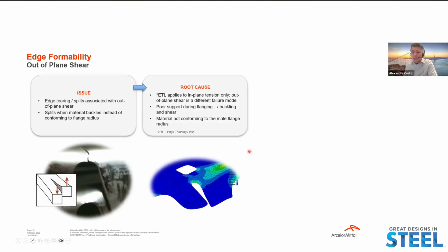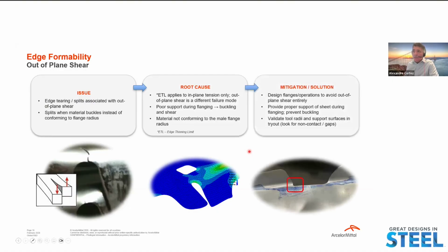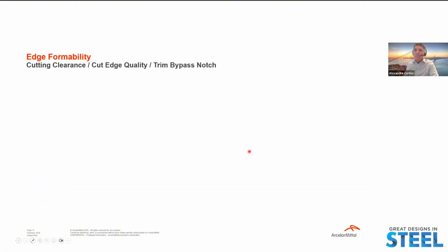As a root cause, ETL applies to in-plane tension, not out of plane shear. It is a different failure mode: poor support during flanging leads to buckling and shear. As a mitigation, design flange operations to avoid out of plane shear, provide proper support of the sheet during flanging, and validate tool radii and support surfaces in tryout.